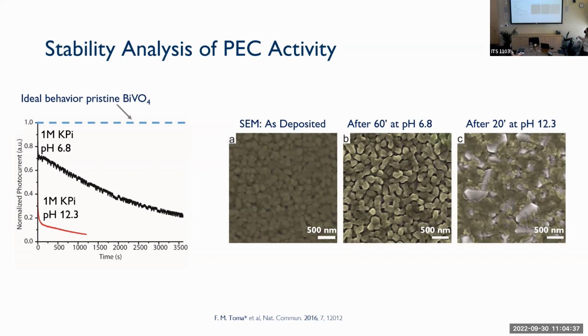Here, because of the lighting, you cannot see it very well, but you saw images earlier. The material is polycrystalline, is granular, but those grains are well defined. And then when you put it in a solution, those grains are not well defined anymore, and they start fusing together. After fusing together, they actually leave the substrate, and this is at 20 minutes at pH 12.3.